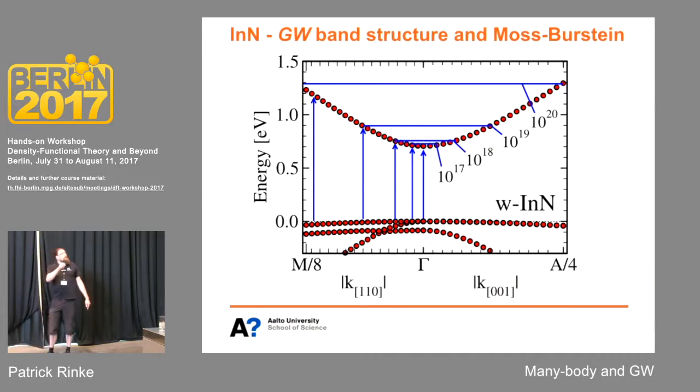What the photon has to do is find another electron that can make a direct transition further out. Like maybe if you're at 10 to the 18, you have to go beyond this to the left, right? So you do your transition out here, but then you need much more energy, right? Because the band curves away from you. It curves away from the valence band, and the valence band curves away, right? So you're measuring a value that is larger than the band gap, so you seemingly have a larger band gap, right? Because you just can't measure down here, right?